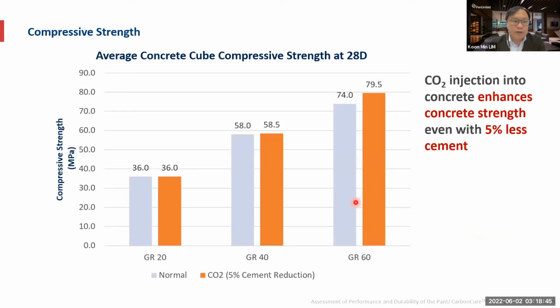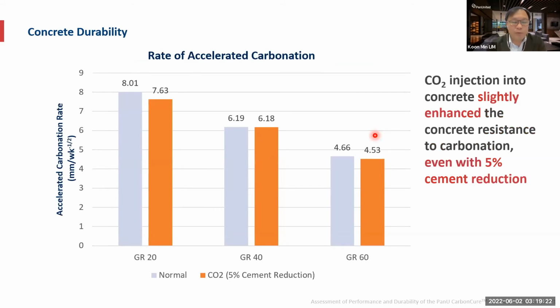Okay, so for the next few slides, we will be comparing the normal concrete against CO2 mineralized concrete. But bear in mind that for this CO2 mineralized concrete, there's a 5% cement reduction of the original mix design for the normal concrete. So very quickly, when you look at the compressive strength for your grade 20, 40, as well as 60, the strength exhibited by the CO2 mineralized concrete is quite comparable to that of the normal concrete, even with a 5% cement reduction.